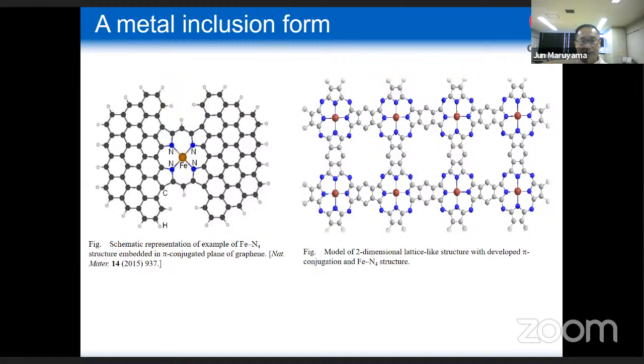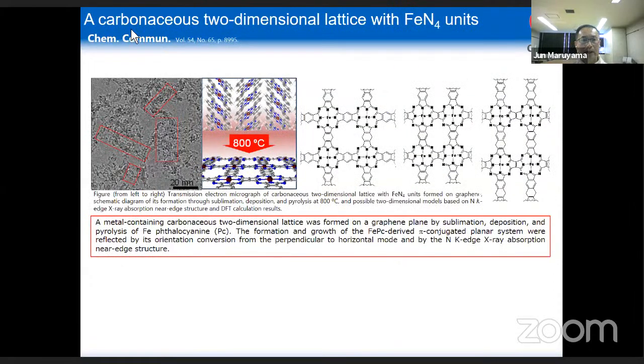And actually, these materials are easy to synthesize. One of the raw materials is iron phthalocyanine, and just sublimation and deposition and pyrolysis can make this two-dimensional layer lattice-like structure containing iron and nitrogen. This is a TEM image showing iron particles aligned in a regular way.